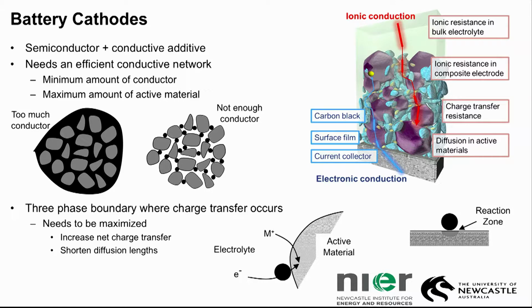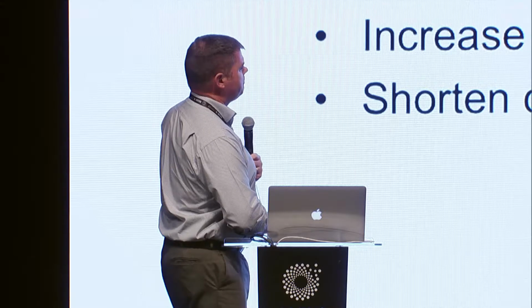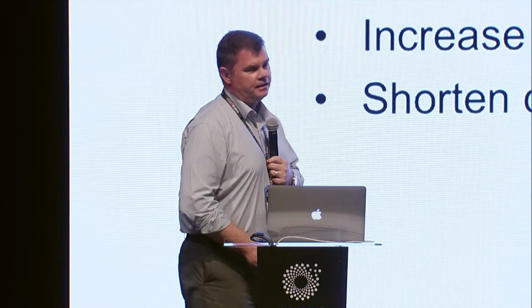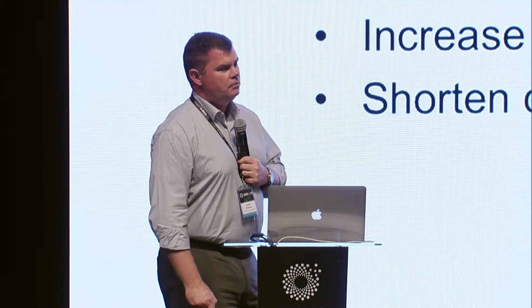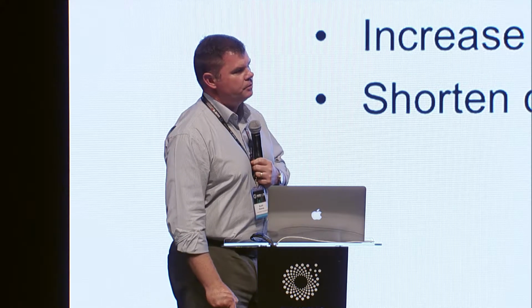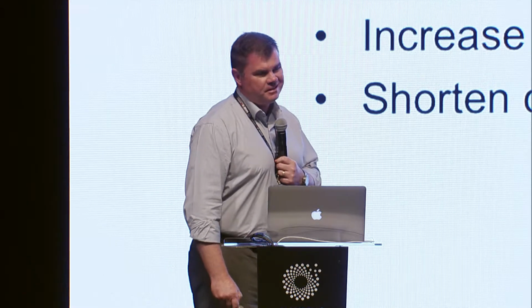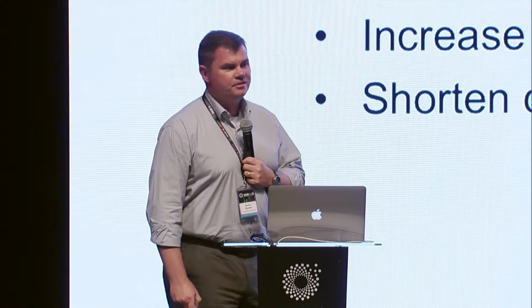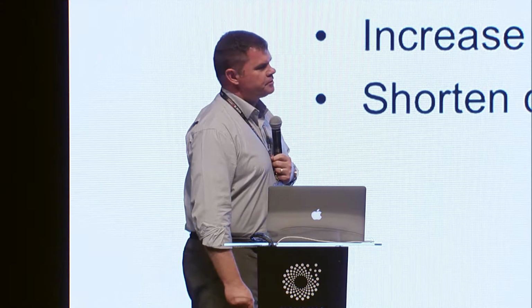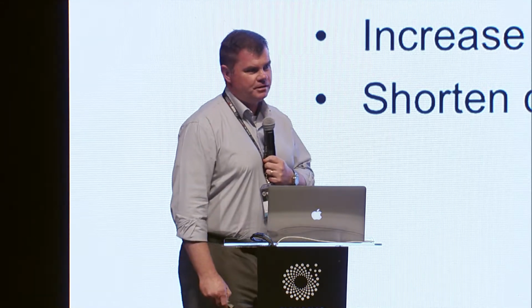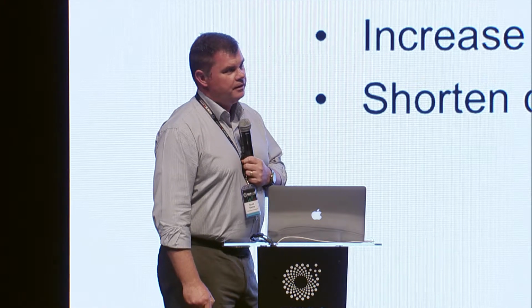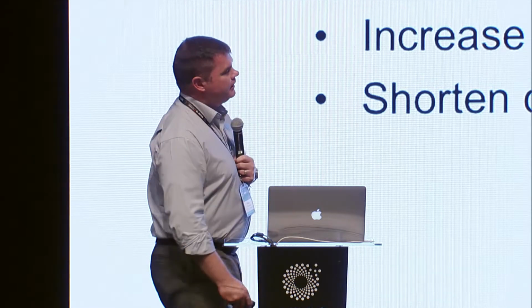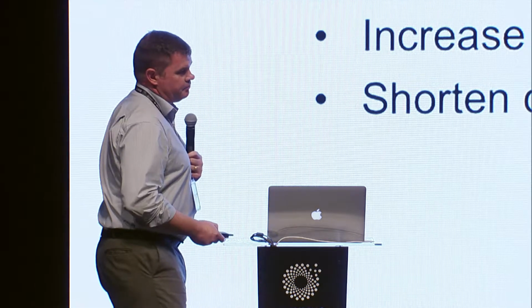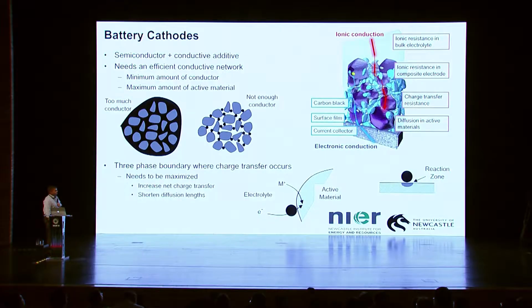Now, what's critical about this is that we need to maximize the amount of carbon efficiency in our cathode, or conductive efficiency in our cathode. What we need is excellent conduction within the cathode itself. Being a semiconductor material, it can't work by itself, it needs that conductor. But we also have to maximize the amount of active material that's there as well. Unless we get that balance right, we can't begin to optimize these types of systems.